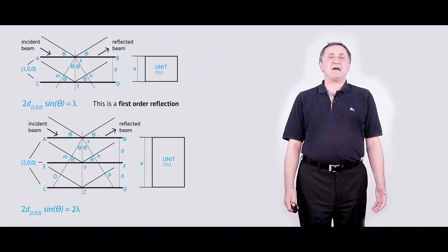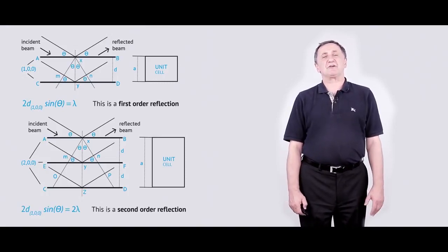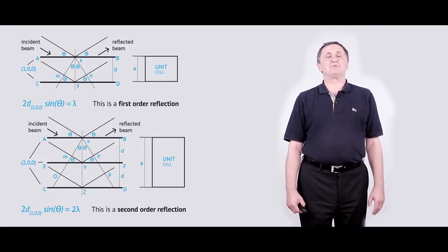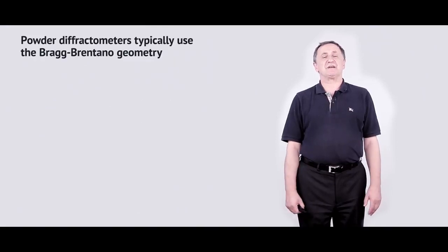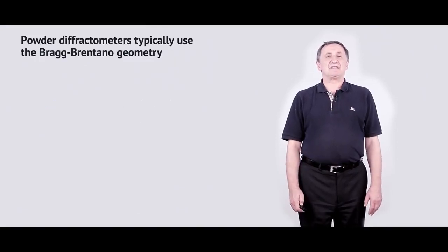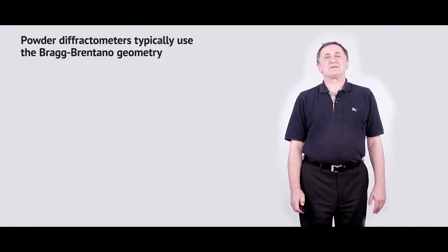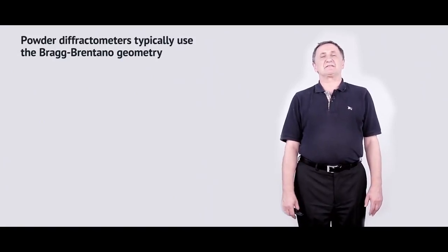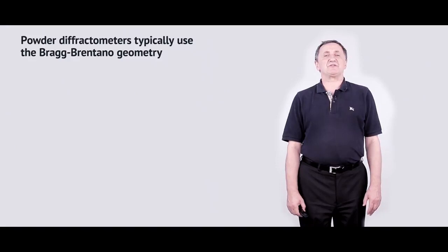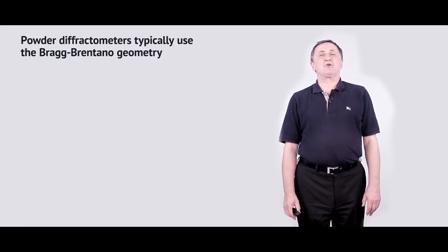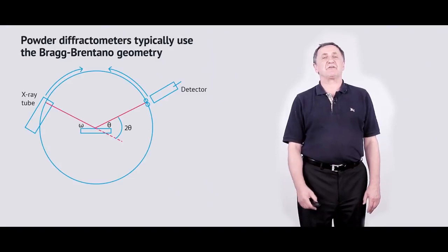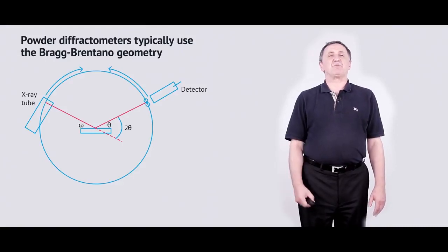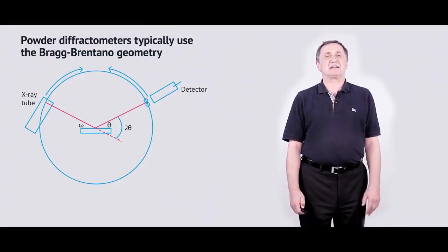And if so, then by measuring the interference picture, one can calculate d_hkl, and knowing d_hkl and assuming the type of the crystal structure, one can calculate the characteristics of any unit cell. That's the whole idea. Of course, there is not one but many parallel hkl planes in our material, and because of that we can talk about first order reflection, second order reflection, which means that we expect not one but several peaks corresponding to the reflection between these selected hkl planes.